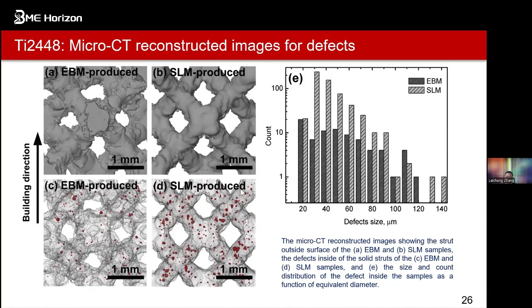We can show the defect count and the size distribution in the EBM and SLM produced specimens according to figures C and D. You can see the number of defects inside the EBM produced sample is less than the SLM manufactured sample. This is especially true for the pores with equivalent diameters of 30 to 90 micrometers. You can see from the color, the dark color is from EBM, and the light color is from SLM. From 30 to 90, the numbers are smaller, that's the number of the defects.